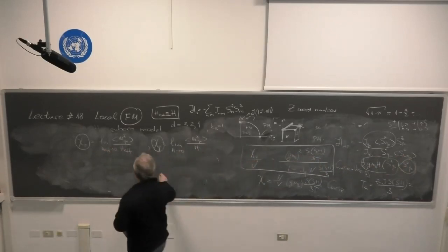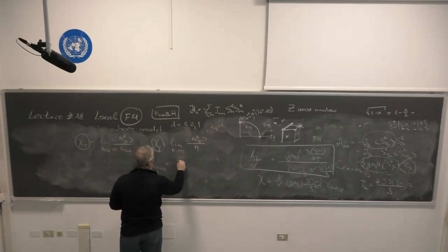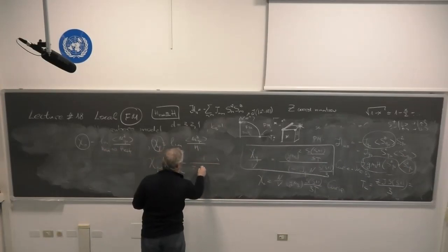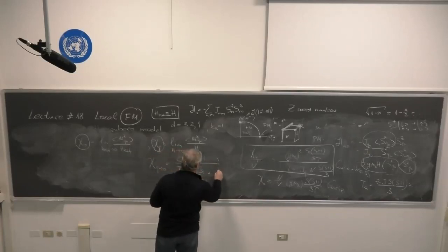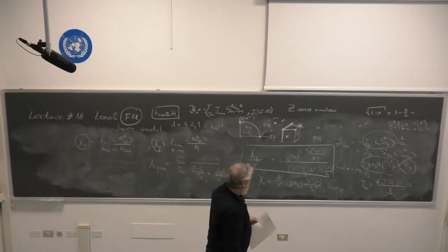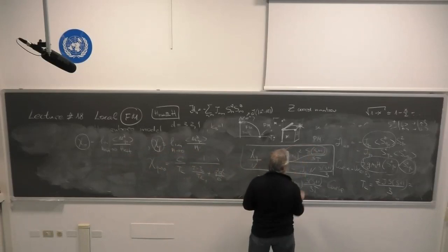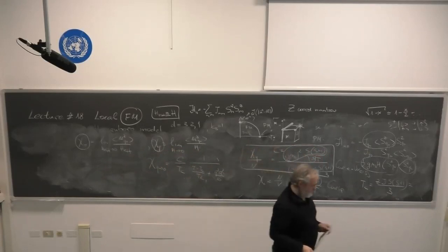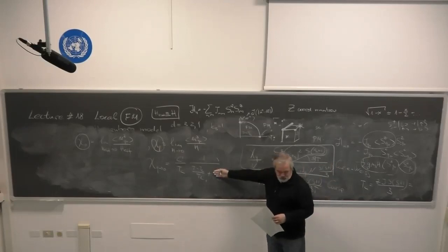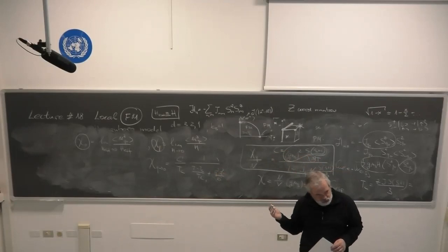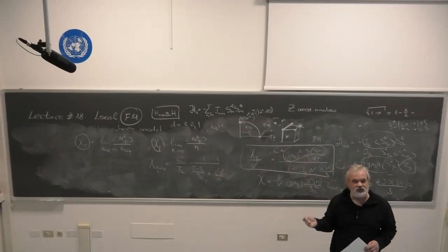for a simple cubic lattice, I have chi(q) as q goes to 0 equal to C over Tc, 1 over (T minus Tc over Tc plus q squared a squared over 6). This is C, oh, with a 3. Good. So without this term, namely if q is equal to 0, we reproduce what we obtained through the molecular field theory. However, now we include the small q into consideration. Therefore, we included the fluctuations associated with the existence of different moments.